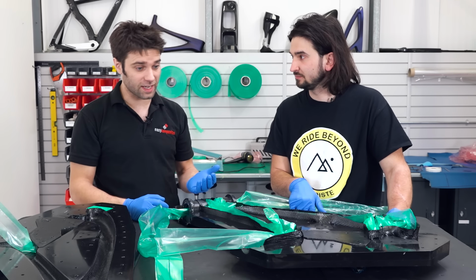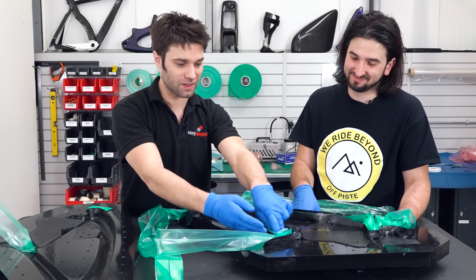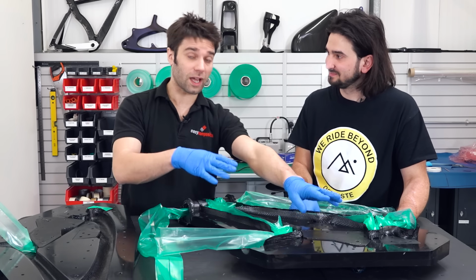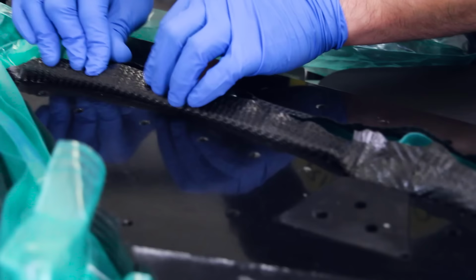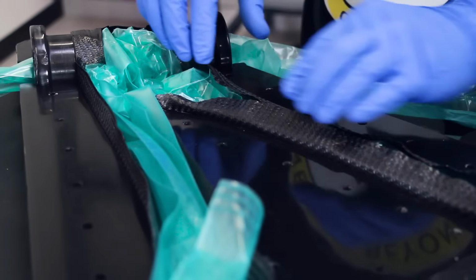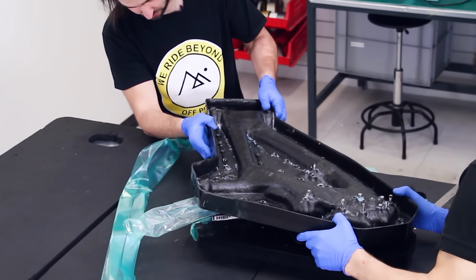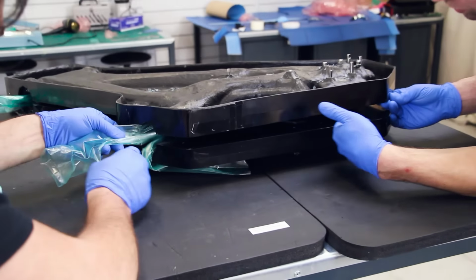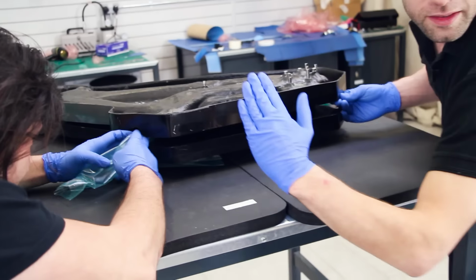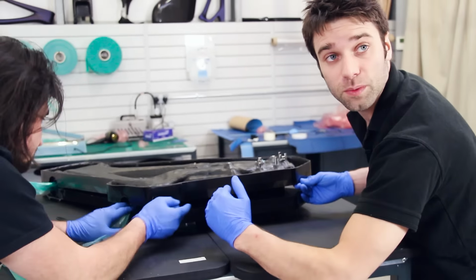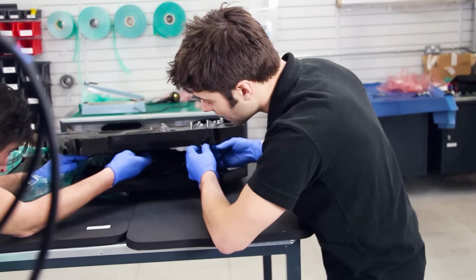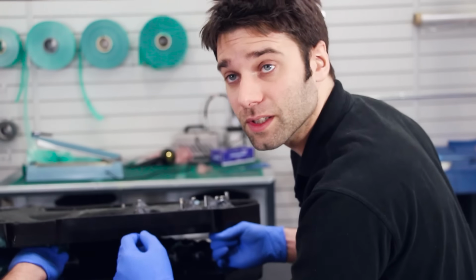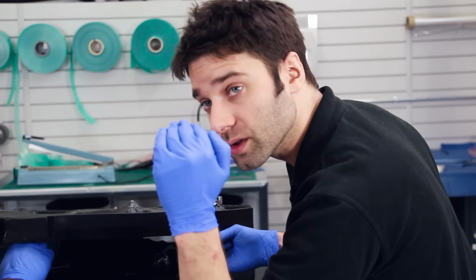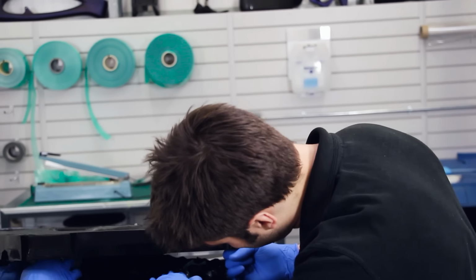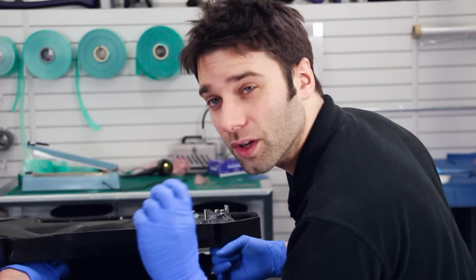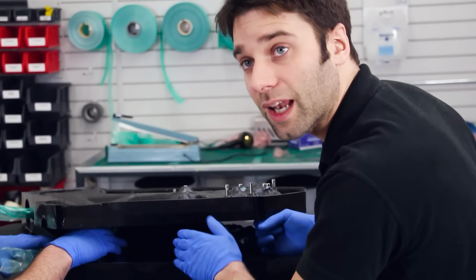This is pretty high stakes, so presumably it's just like we did with the shock tunnel inserts, making sure everything's folded in neatly, that you get no material trapped on these barriers. We've got the moulds just held slightly open. Obviously we tried to get all of those laps to fold in as best as we could, but to make absolutely certain that they're down, we can gradually close the mould and go in through the gap and just push the laps in to make sure that they never get pinched between the 2 clamping faces.